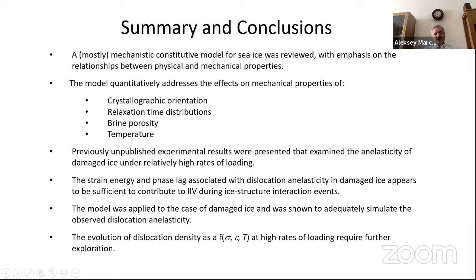Yeah, I can ask, because it's very interesting. When you consider ice, you mentioned today granular structure, then brine pockets and dislocations. If you look at grain size, it will be some millimeters, maybe centimeters. Brine pockets are much smaller. We cannot see them on thin sections. We see brine pockets in a microscope, so they are probably some microns or smaller. And dislocations are on the atomic scale, even much smaller. So when we look at dislocation dynamics, we are in one type of scientific terminology.